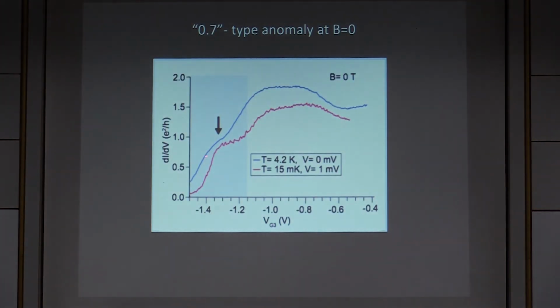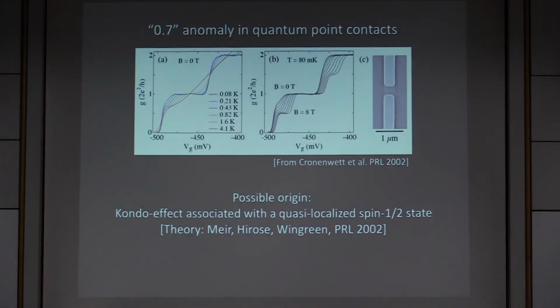So if I raise temperature, what I find is, again, a plateau that is approaching 1.8, but there is a shoulder over here. And the same shoulder I can find if I measure the conductance at finite voltage, well above the gap of the superconductor at low temperature. So this shoulder we interpret as a reminiscence of the 0.7 anomaly effect. It's well known in quantum point contacts.